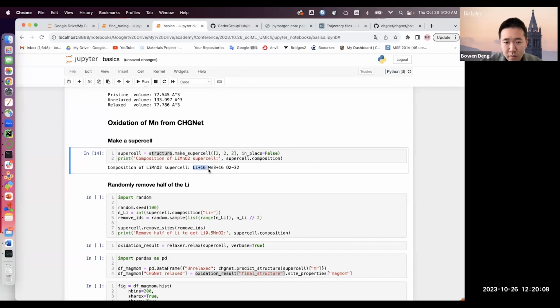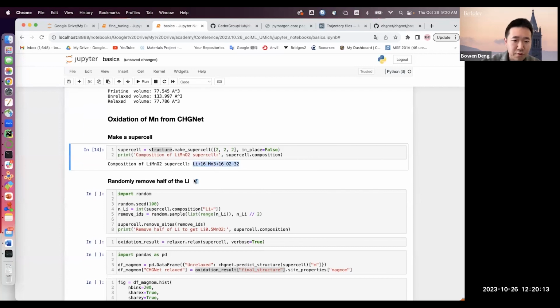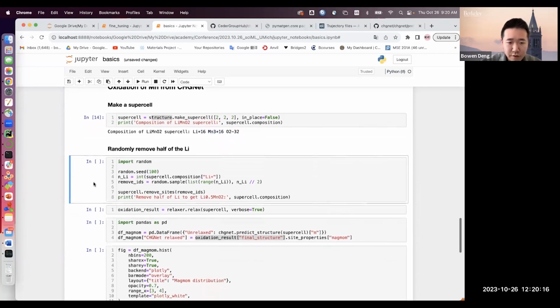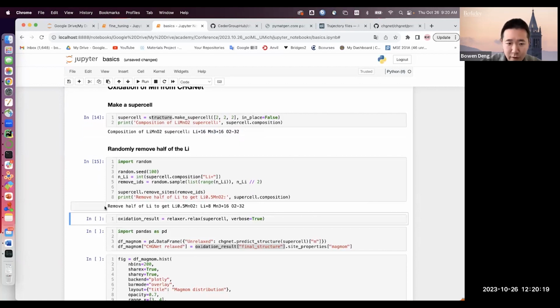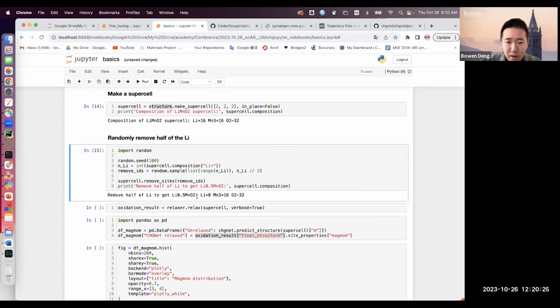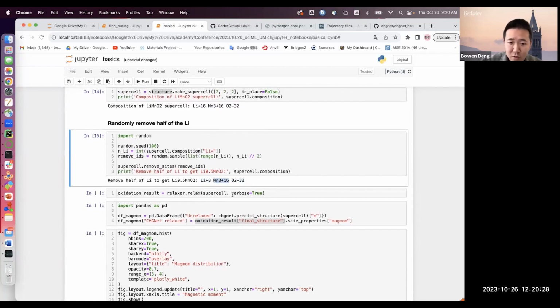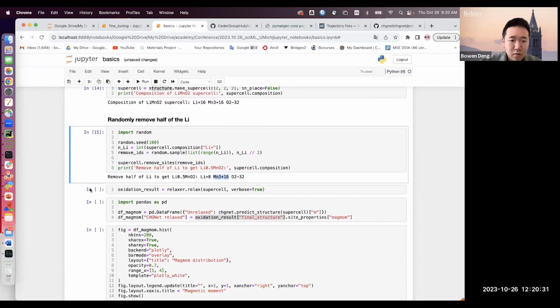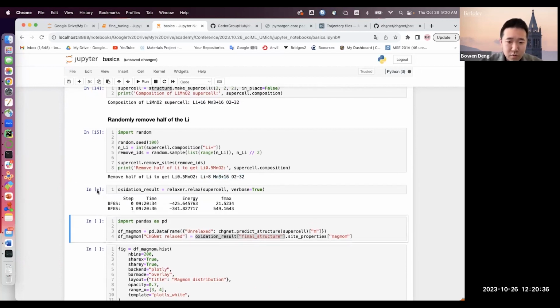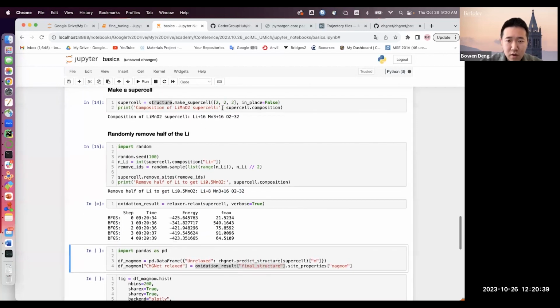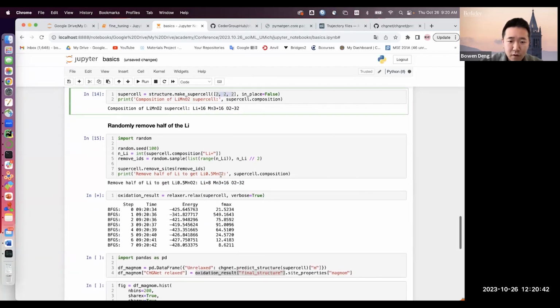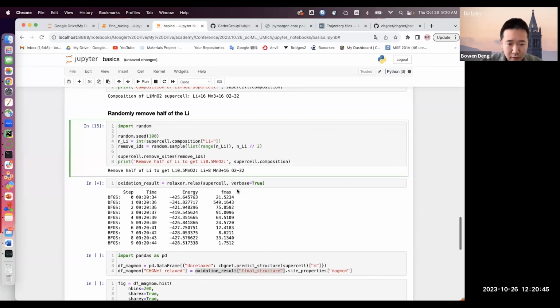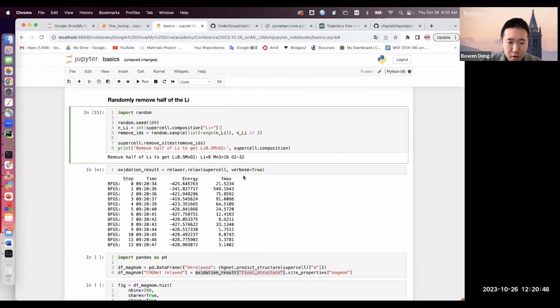So you can see the composition of this supercell. We have 16 lithium plus, 16 manganese 3 plus, and 32 oxygen 2 minus, and this is charge neutral. And we randomly removed half of the lithiums in this system. So you can see after we remove half of the lithium, we get only 8 lithium ions. And now this is charge unbalanced. And we want to see which of these manganese ions will be oxidized. So we can just perform a relaxation with CHGNet. This will be a little bit longer since this cell has 8 times the atoms of the previous example. But still, I think it can be completed in around 1 minute.